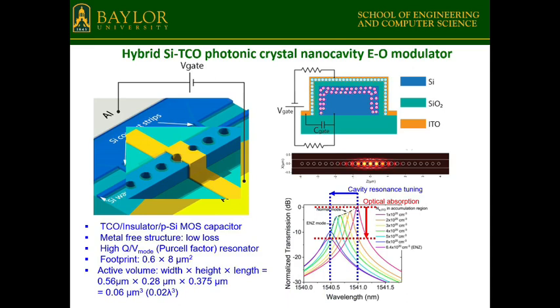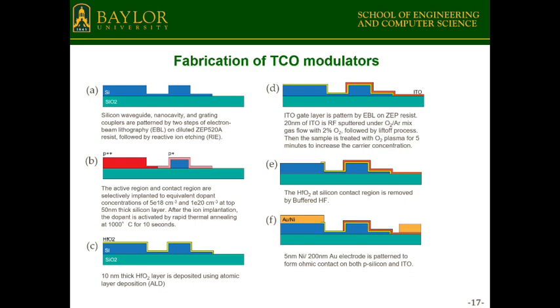And we make this modulator, and this is the transmission. When you apply a voltage, you can shift the transmission, so you can switch the modulator on and off. And this is fabrication. We need to use very sophisticated tools like electron beam lithography and reactive ion etching to form the waveguide, and then we can dope it to form a contact region, and then we use atomic layer deposition to include this high dielectric constant insulator, and then we use sputtering and liftoff to put the gate material on top of the waveguide, and then we use metal to make the metal contact. So this is how the process goes. It only shows the major steps, but actually this requires more than 30 steps of semiconductor device processing.